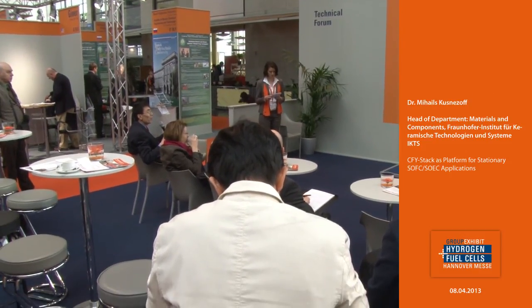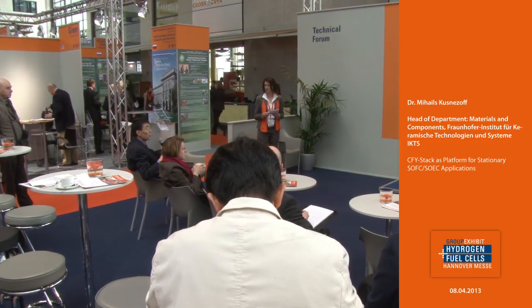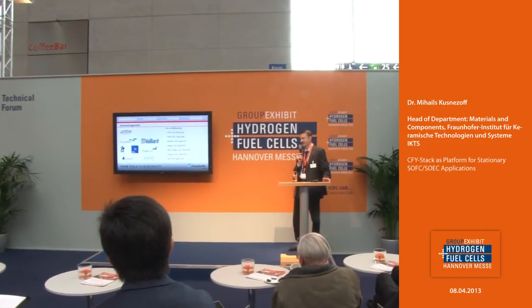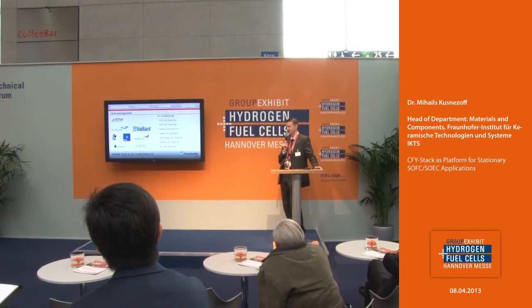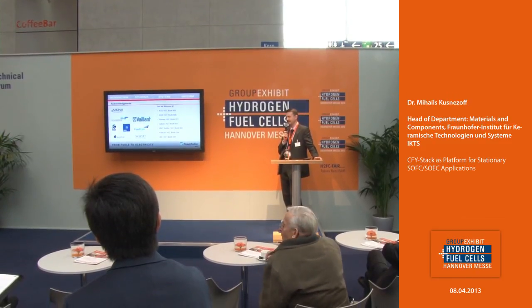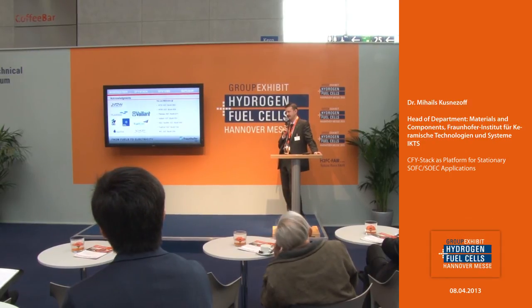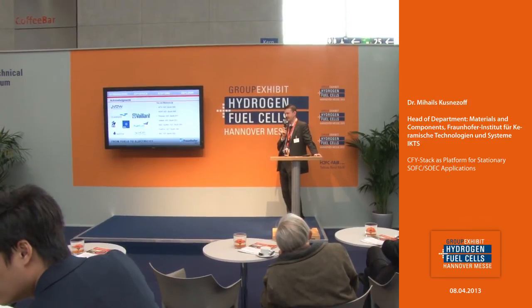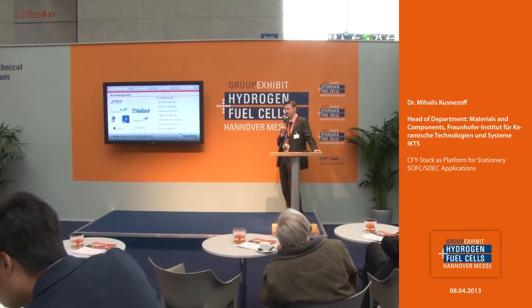So how much is the pre-reforming? How much internal reforming? Yeah, we have approximately 10 to 12% of methane in the fuel which is going into the stack, at the stack inlet or stack module inlet. Then rest is the hydrogen, or? No. It is pre-reformed natural gas, so the rest is hydrogen, CO, CO2, and water.